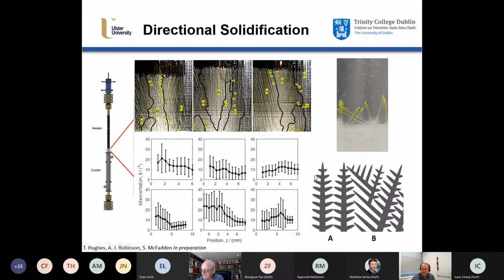But in other cases, you will see that it deviates from Walton-Chalmers. In fact, it doesn't converge down to a preferred orientation. And in some cases, it goes a bit more chaotic. And then in some cases, it diverges and then it converges. And in particular, we have examples of the exact same scenario under the same process conditions with the same material, remelted back and regrown, and sometimes obeying Walton-Chalmers and sometimes disobeying it completely.